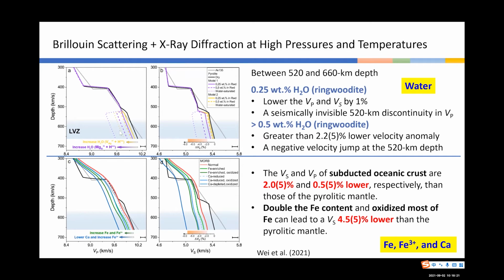But the problem is, at the same time, look at the Vp, this dashed purple line here. That means we are going to have a negative velocity jump at 520 kilometer depth. This was never reported by seismic studies. So we think that it's very difficult to use water to explain the observed low velocity anomaly at the bottom of the transition zone.